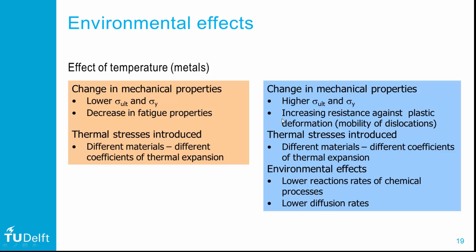The influence of environment should not be limited to the medium, but also to ambient temperature. In general, an increase in temperature reduces not only mechanical properties but also the fatigue properties of materials — mostly relating to material resistance, but also increased thermal stresses within a built-up structure. At low temperatures the effect is opposite, partly due to reduced water vapor in the air, which reduces reaction and diffusion rates. Hence an aircraft flying at cruising altitude implies a cabin pressure load cycle at very low frequency, but as it flies in a non-aggressive and cold medium, its contribution to fatigue is effectively low.